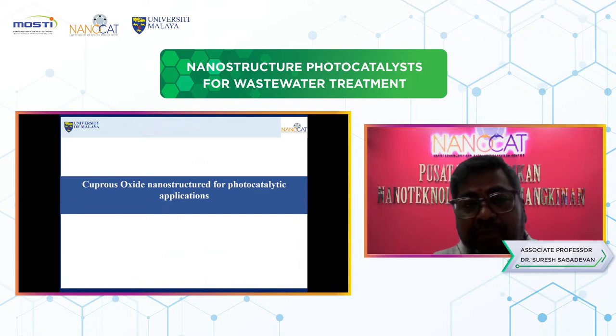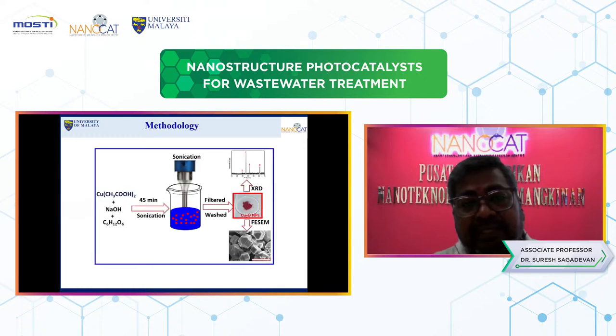The first material I'm going to discuss is a nanostructure for photocatalytic applications. This one is a very good potential material for wastewater treatment. First, we prepared this sample using copper acetate monohydrate, sodium hydroxide, and glucose mixed together for 45 minutes of sonication. After that, you can see that we prepared this copper oxide nano powder, and then